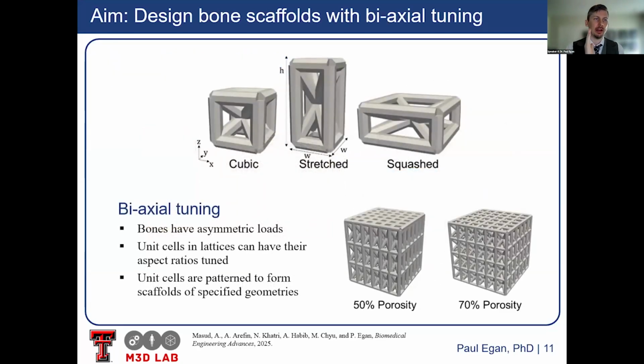And so our design, we have the basic cubic design, that's symmetric, the stretched one, which because we're extending it in this direction, we expect a higher elastic modulus in this direction because those diagonal cross beams are more aligned with the loading direction, and then squashed would do the opposite. But what you're getting here is you're increasing the longitudinal elastic modulus in one direction and then increasing how much the biological growth can occur in the other direction because you have these larger pores.